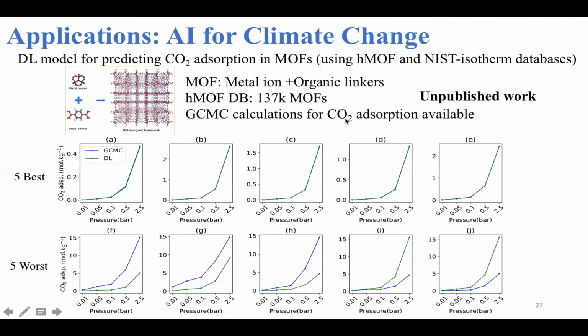So using an 80-10-10 training, validation, and test split, again, we try to predict the multi-output model for CO2 adsorption at different pressures. So these are the 5 best and 5 worst predictions. So again, these are the 5 bottom ones. So even the best ones are definitely really good, and the worst ones also have a good trend, and they are not systematic, but some of them are high, some of them are low with respect to the grand canonical Monte Carlo.